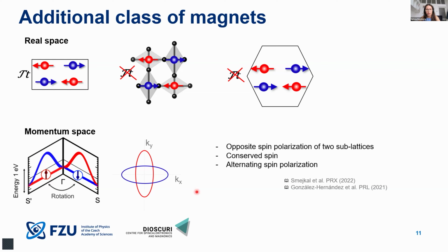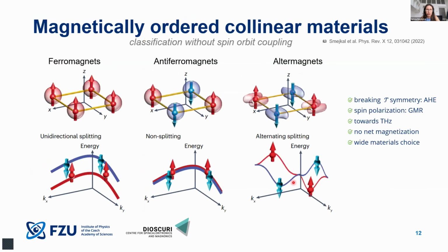So when I come back now to the cartoon, we have a class which to some extent combines the properties of ferromagnets and antiferromagnets. However, it also offers features beyond both of these classes, such as this anisotropy. That is something not existing in any ferromagnet: depending on the crystal direction, the spin polarization of the charge current would be alternating. So this sort of anisotropic character is not only a combination of ferromagnets and antiferromagnets, it simply goes beyond.